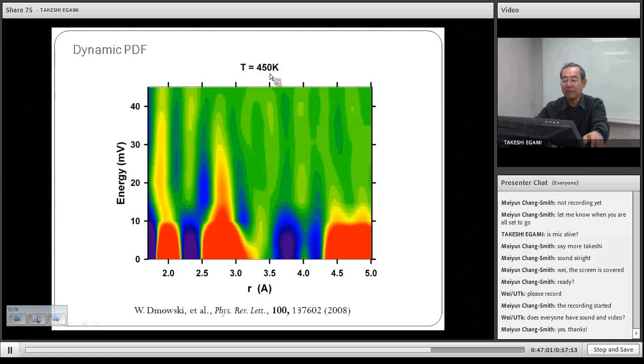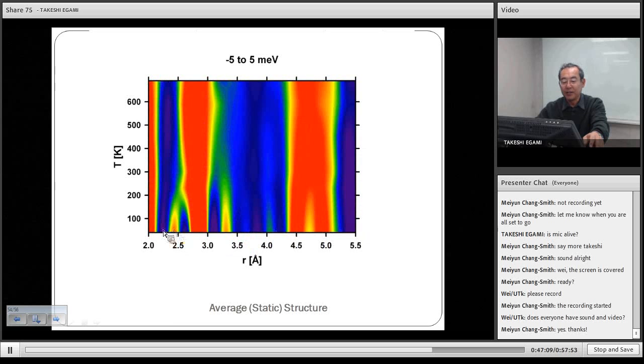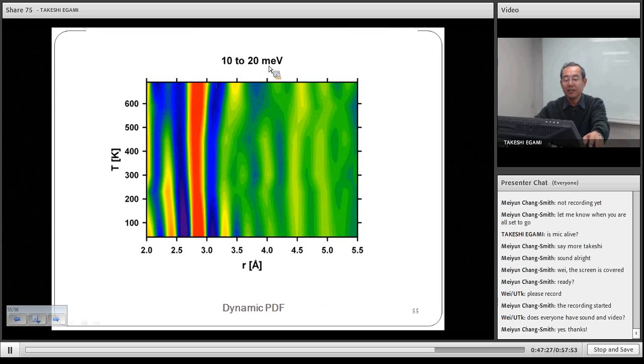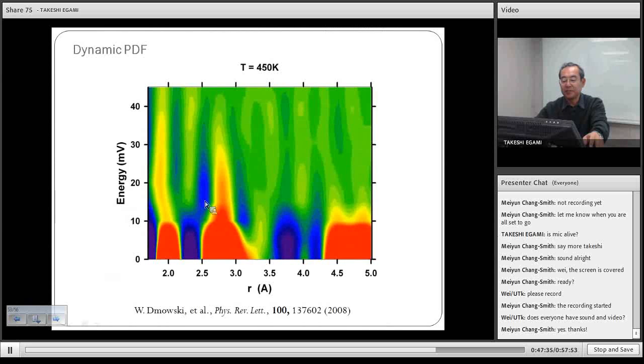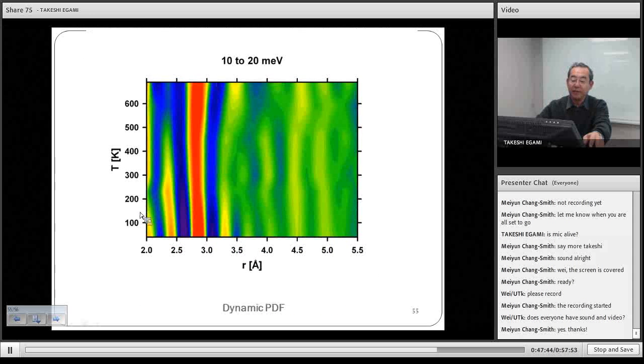So at this frequency, at this temperature, for instance, this is above the Curie temperature. So there is no split. There's no polarization. But at low temperature, the polarization shows up. Okay, these are polarizations. And then it disappears around room temperature. But if you go to high frequency, this is the 10 to 20 millielectronvolt, okay, this intermediate range of frequency. This is low frequency. This is high frequency. Then you see this side branch due to polarization, okay, all the way up to 600. This one persists up to 600, and then only here they merge into one, right? It splits like that into two.